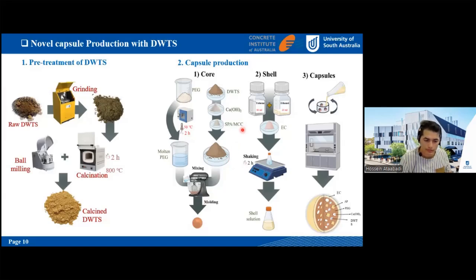For the capsules, we need a thin layer of coverage that prevents the core material from reacting with the cement matrix. We need to provide a shell or protective layer. For the shell, we use another polymer called ethyl cellulose, a natural polymer under the cellulose category. After some preparation, we have a shell solution, and afterwards we cover the cores with the shell material to produce our capsules.